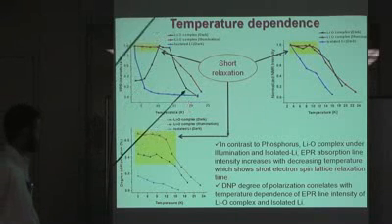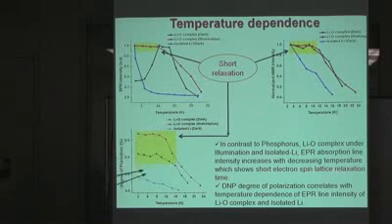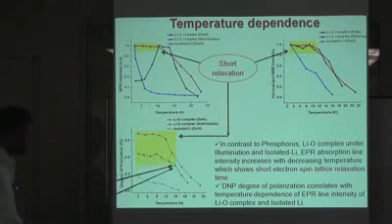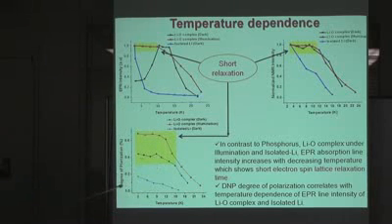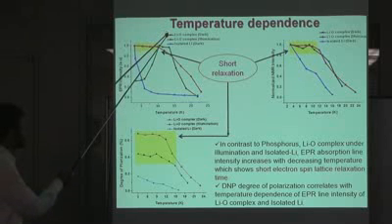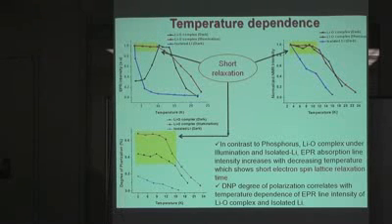low temperature. A similar phenomenon occurs, and it almost correlates with the EPR intensity, for the dynamic nuclear polarization, degree of polarization versus temperature. Here also you can see the temperature dependence of degree of polarization is almost constant in the lithium oxygen complex, in dark and in light also.